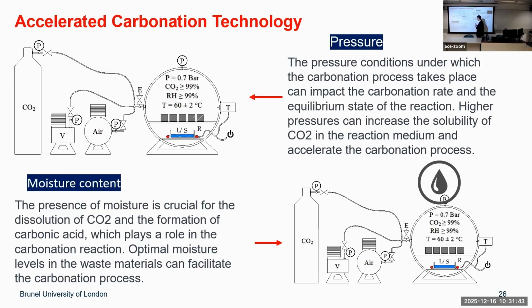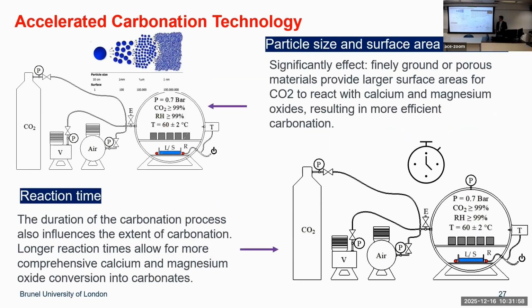Moisture content is sometimes called subcritical moisture content, particularly in semi-wet and semi-dry carbonation. Then you have particle size and surface area, obviously. Smaller particle size means higher specific surface area, a higher chance to contact carbon dioxide and moisture, to improve the carbonation reaction time. So you can shorten the time, which is better.